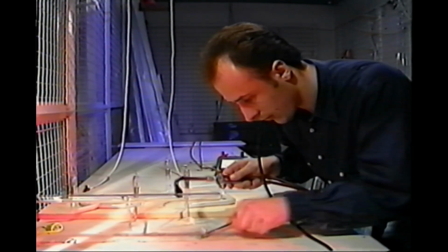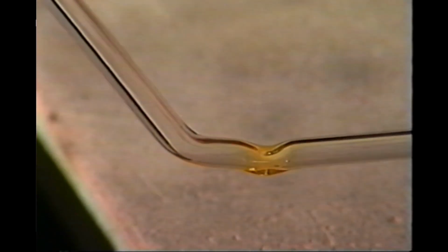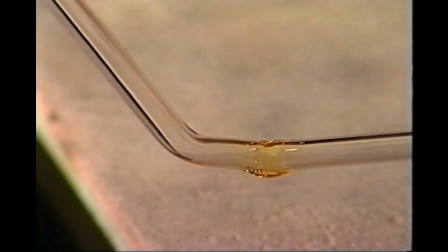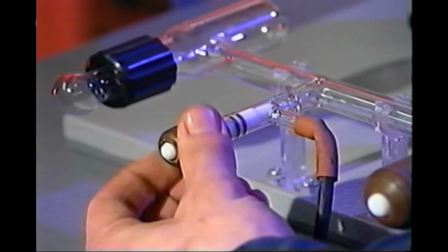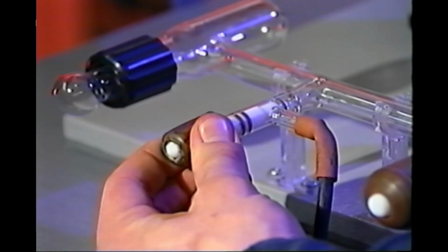Seal the tubes onto the glass manifold. Try wherever possible to process 2 tubes at a time to increase output. Tubes pumped together must be the same diameter, the same rare gas filling, and have approximately the same tube footage. After sealing on, close the air admittance stopcock.